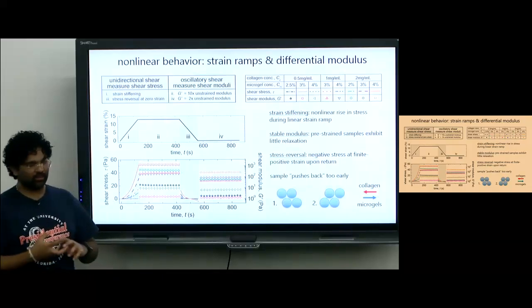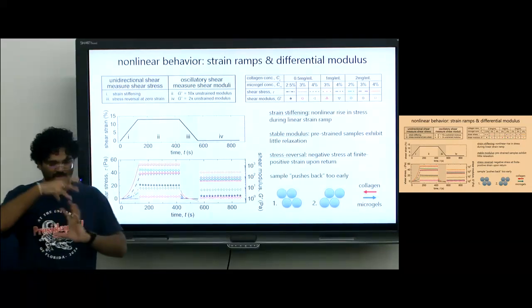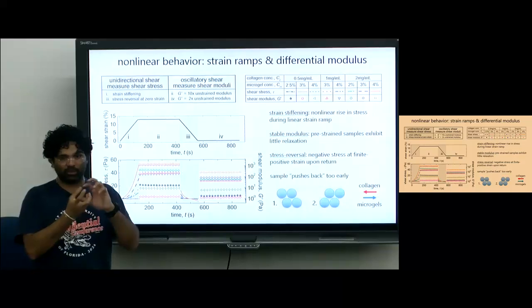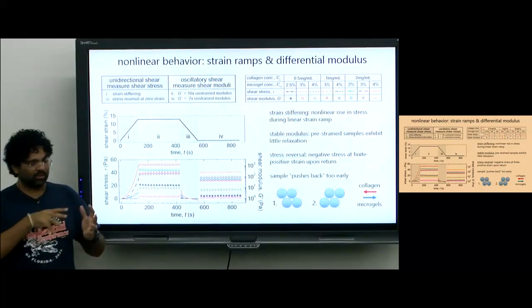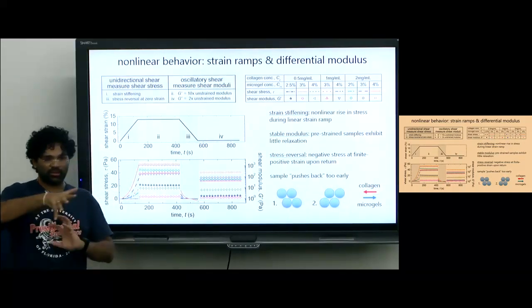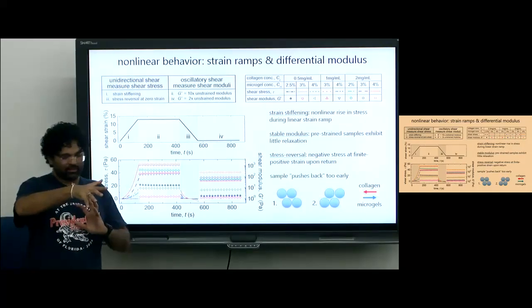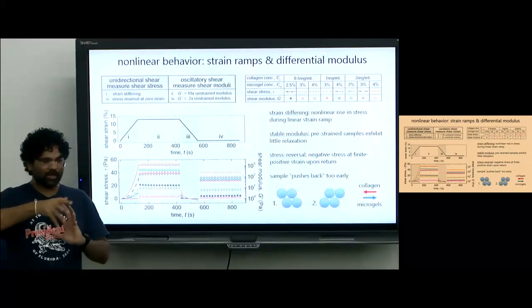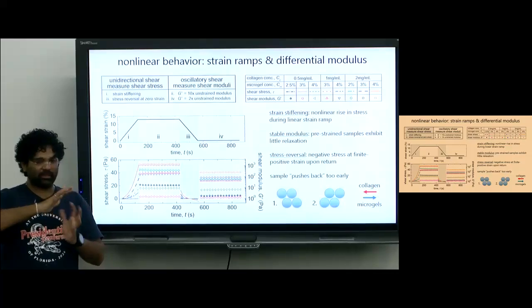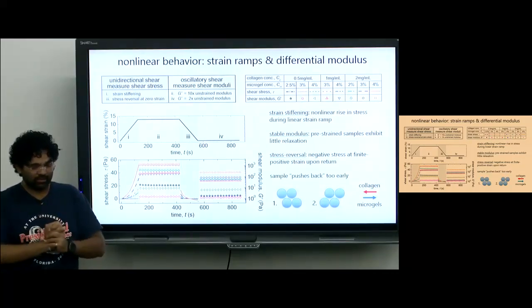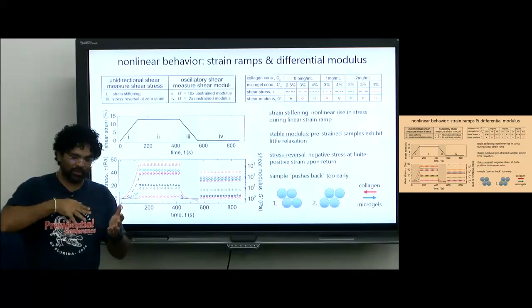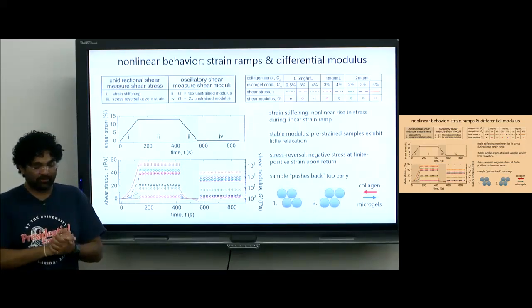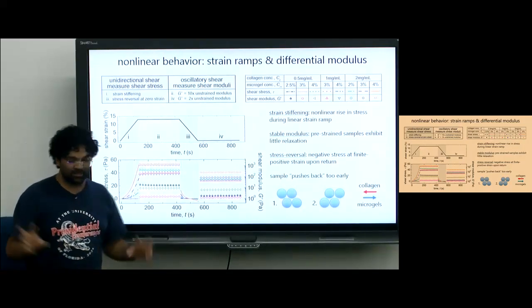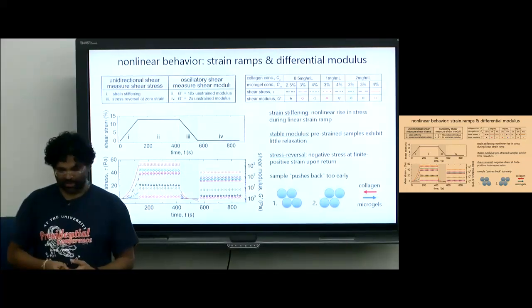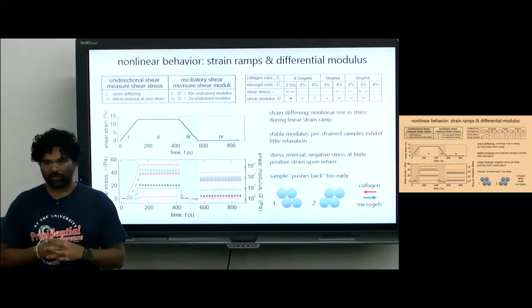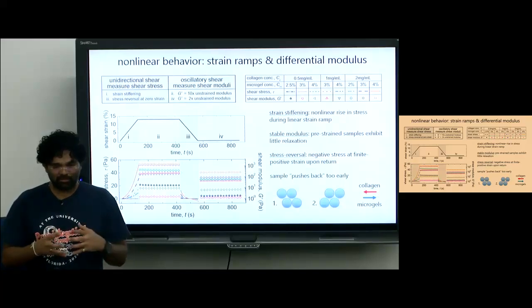And it happens because we can think of this composite material as a bunch of fibrous networks with the porous space filled with these soft spheres. When you shear them, the collagen would strain stiffen, and then when you go back to zero strain, the microgels, because of the reconfigurability, resist your going back to zero strain. So then what happens is it applies an opposite force on your tool, and you start measuring negative stresses. Which demonstrated this idea of shape reconfigurability, or shape memory.